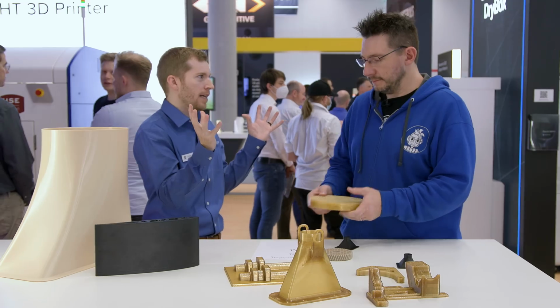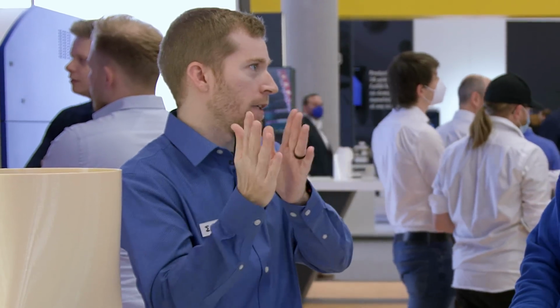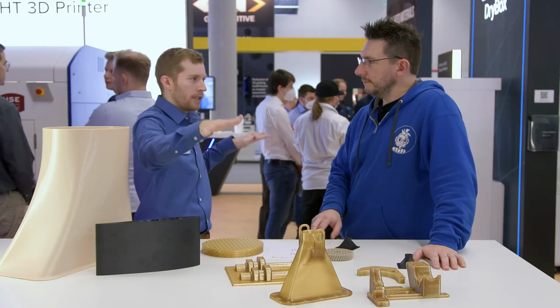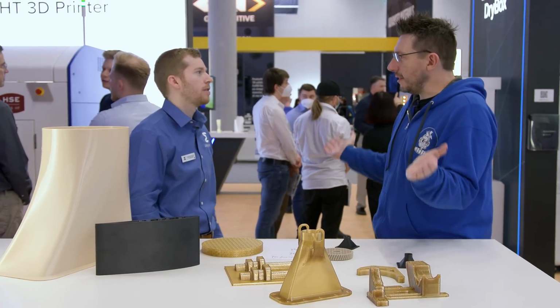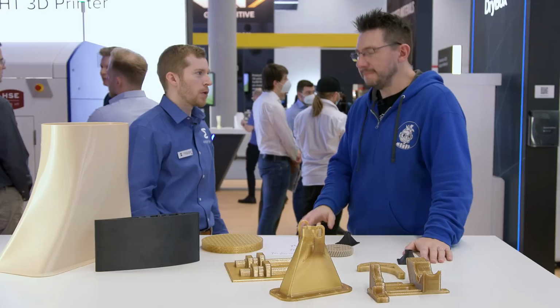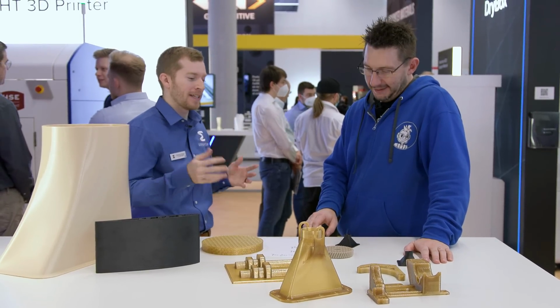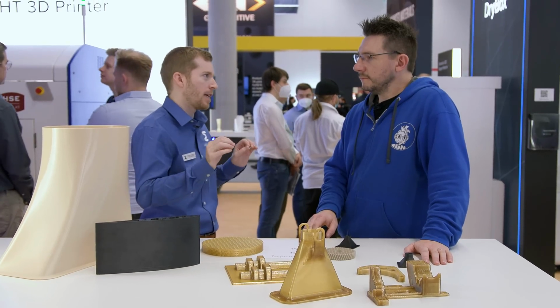And when things crystallize, they actually shrink a lot. So the polymer chains are ordering up really nicely and it shrinks in. So it's really, really hard to make big PEEK parts that are really flat and dimensionally accurate. And that's one of the main things, because in shrinking, they'll pull up from print beds. So you have to be very good at printing and slicing and understanding how to work with these materials in order to get them to come out really flat and dimensionally tolerant.